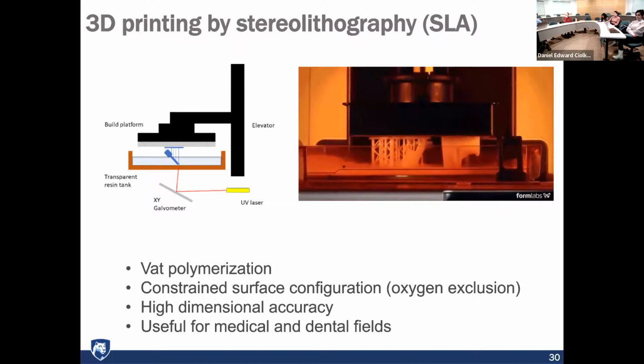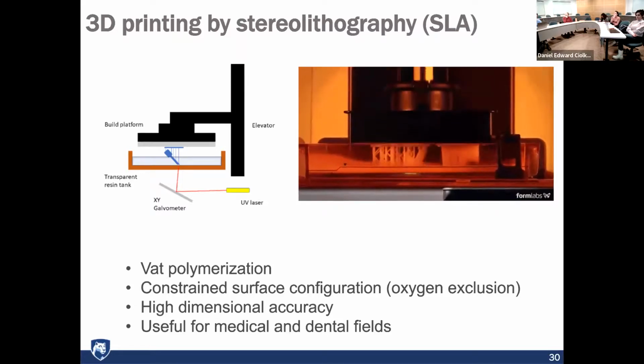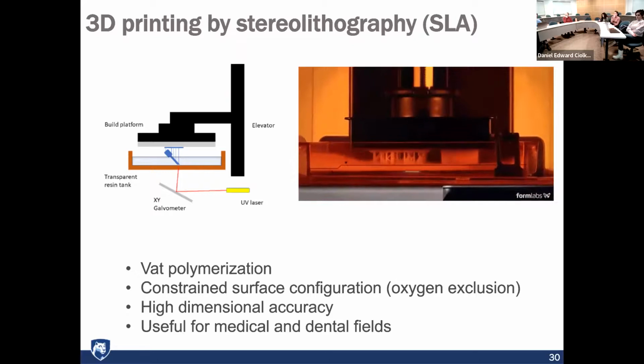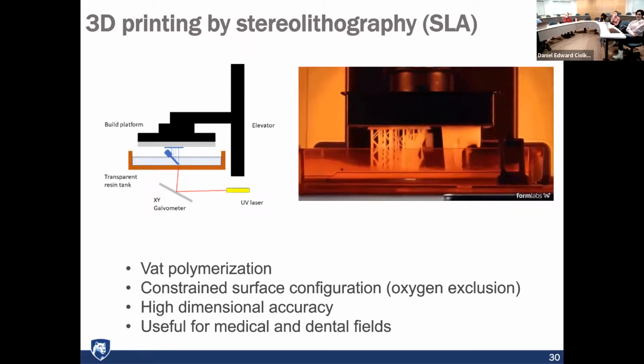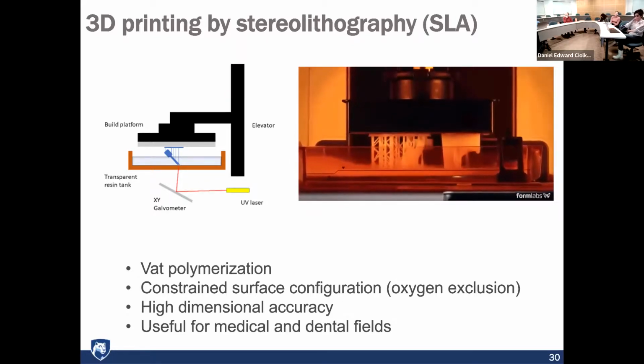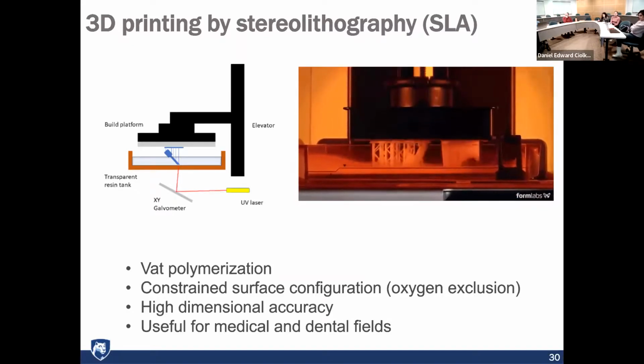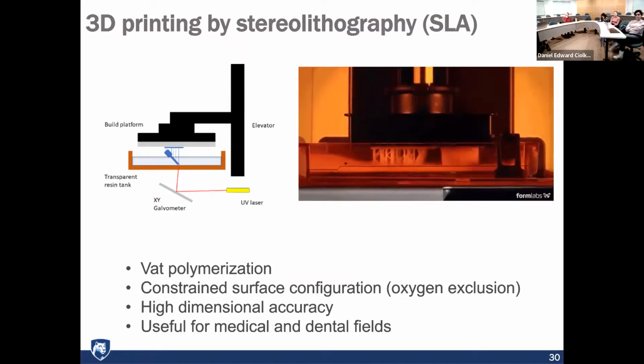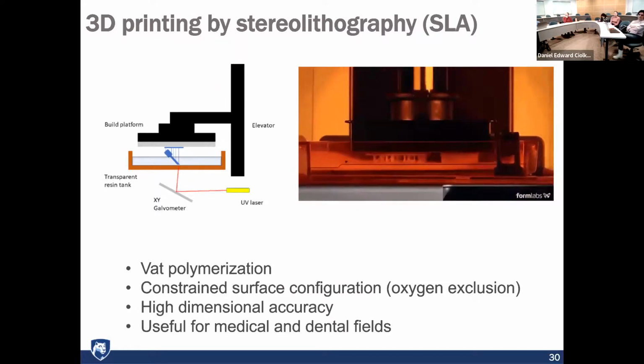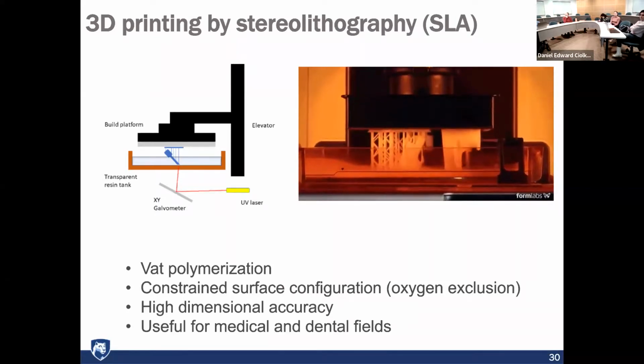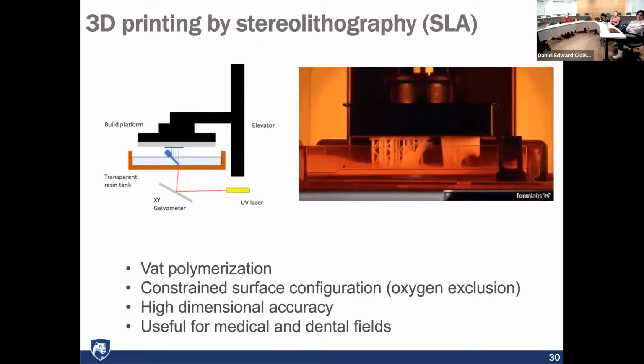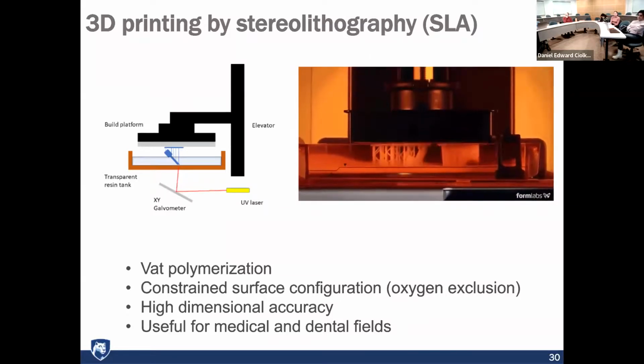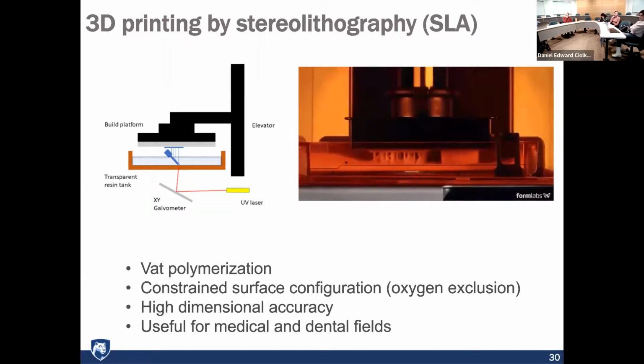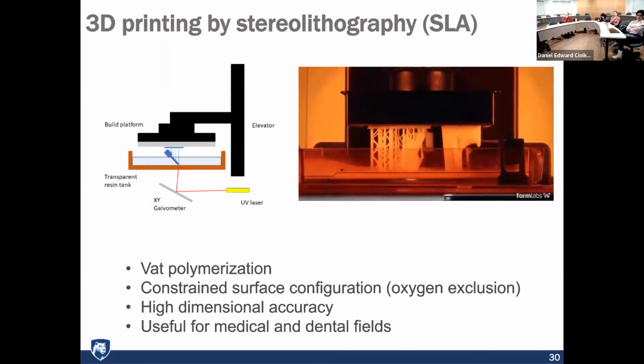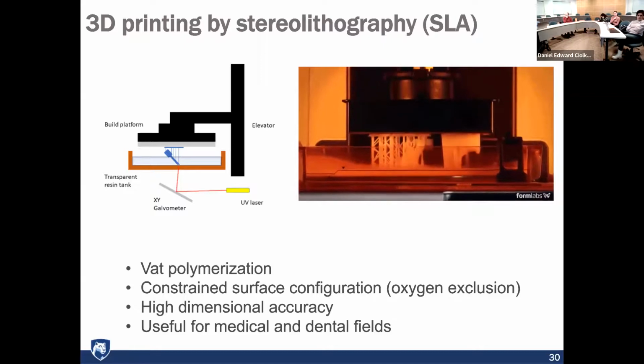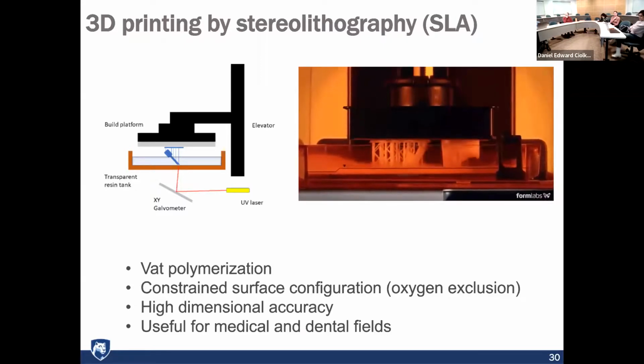And this is a useful process for 3D printing for several reasons. Number one, this is a vat polymerization strategy where you have essentially a bucket that's filled with this liquid material that is, we say, underwater, which gives us this constrained surface configuration, meaning that the polymerization happens under the surface of the liquid. So you remove oxygen from the equation, and oxygen being around is bad for photopolymers or polymers in general. So we take the oxygen away, and make these really nice materials.